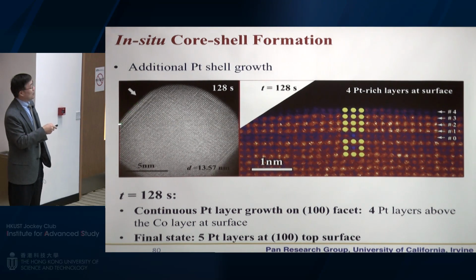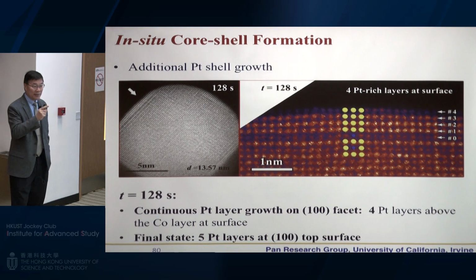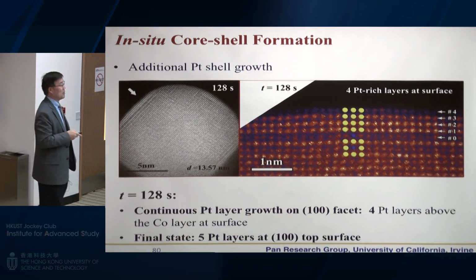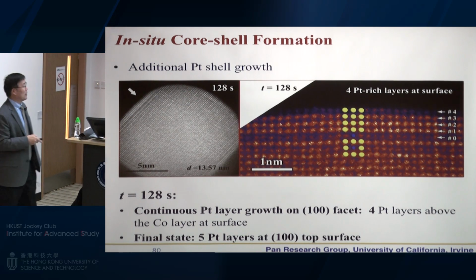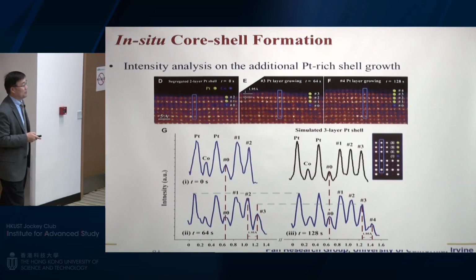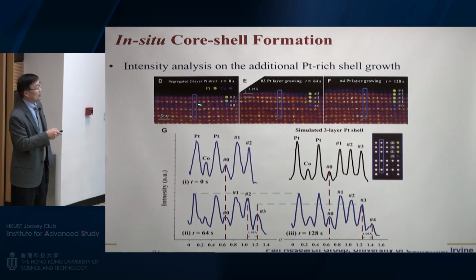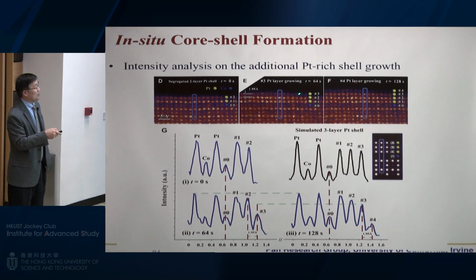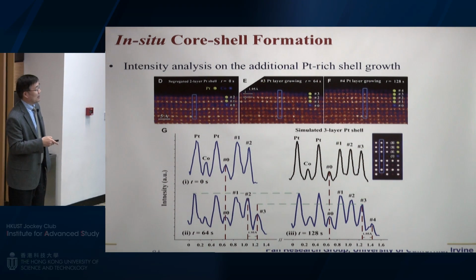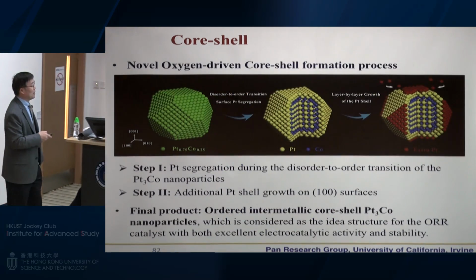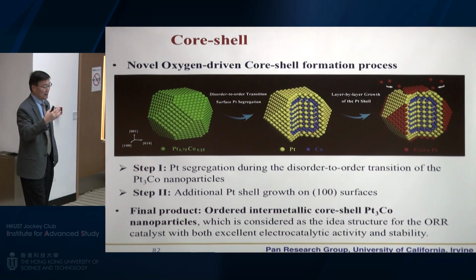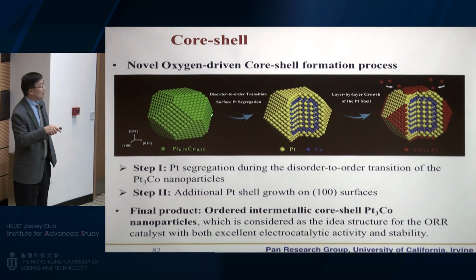You can see this is the edge, okay? Also, this is in contact with another particle. But you can see here 4 layers, but not in the other area. Only the 100 facet will form this platinum multiple layer, not the other surfaces. That means it depends on surface energy. This is a summary of the few steps. One minute later, 3 layers, another minute, 4 layers. And then we see 5 layers as maximum. I think this is limited by the source of platinum in the system. All right, so we see this.